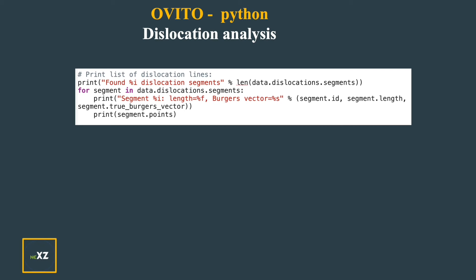Now I print there are five lines here and I print out the dislocation segments. So the dislocation segments here are more than one. So there are two dislocation segments as shown before and I extract them using data dot dislocation dot segments and from segment in data dot dislocation dot segments I extract further information which is a dislocation network information.